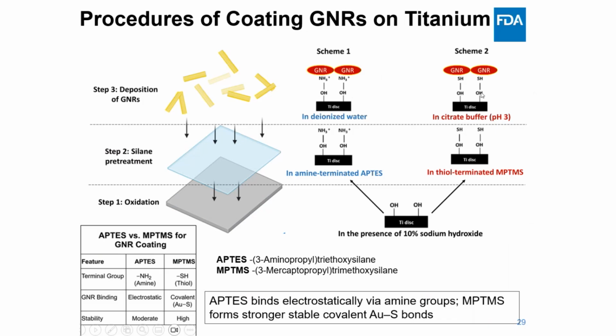To achieve stable gold nanorod coatings on titanium surface, we examine two silane-based surface modification strategies, APTES and MPTMS, each enabling distinct chemical interactions.